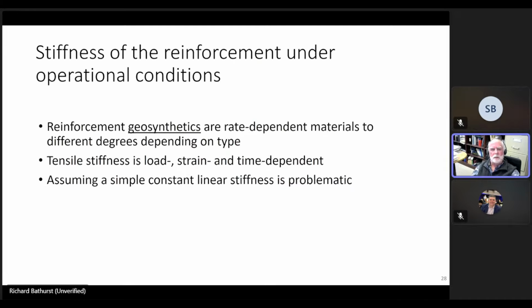reinforcement geosynthetics, the plastic polymer type of reinforcement, are rate dependent to different degrees depending on the type of reinforcement. So this means that the tensile stiffness is load, strain, and time dependent. And assuming a simple constant linear stiffness is problematic and arguably just plain wrong.